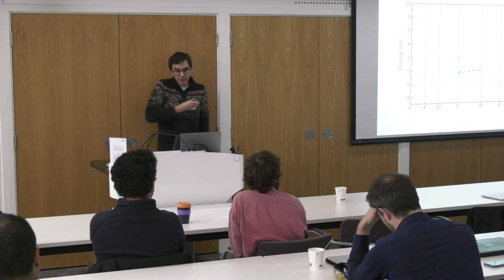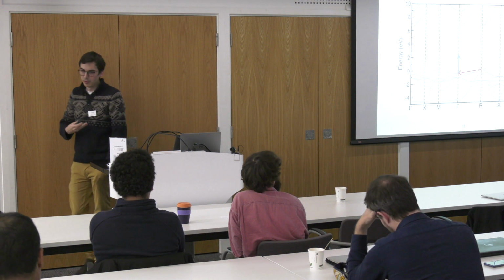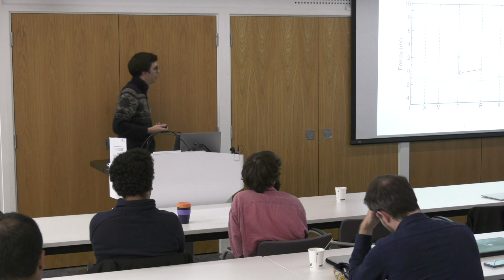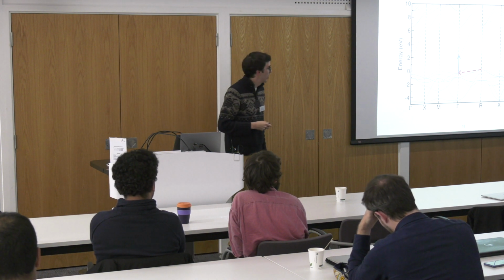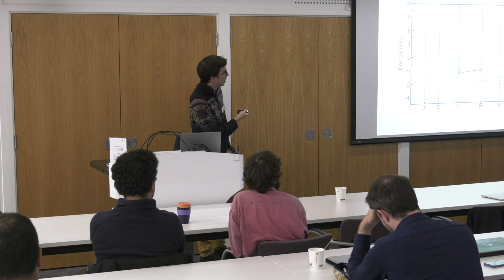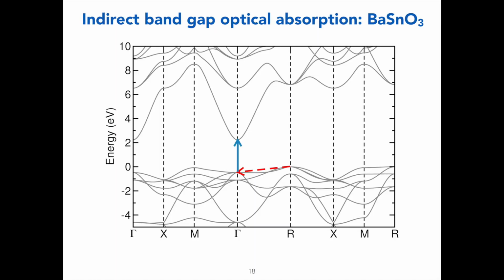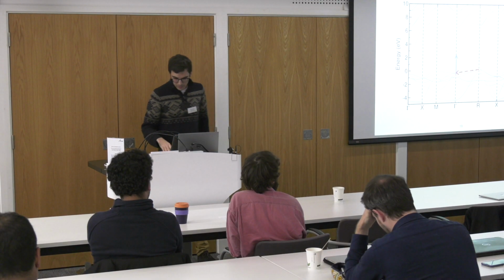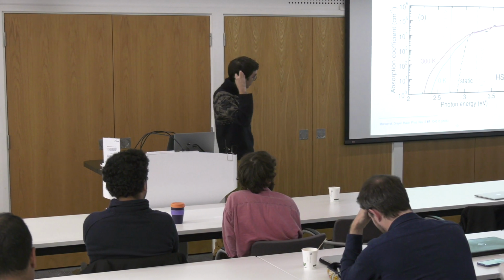And there is a lot of effort trying to optimize these materials and find alternative materials that may be cheaper than the present ones. This is just one such candidate material, and that is its band structure. But the band structure happens to be indirect: the top of the valence band is at the R point, and the bottom of the conduction band is at the gamma point. In order to properly understand the optical properties of this material, you really need to include dynamic disorder to be able to bridge this momentum change. So these are some calculations that we did to do that.